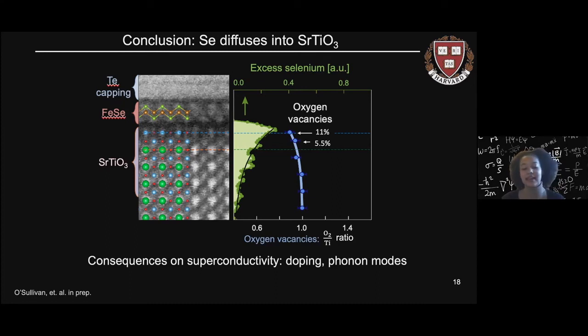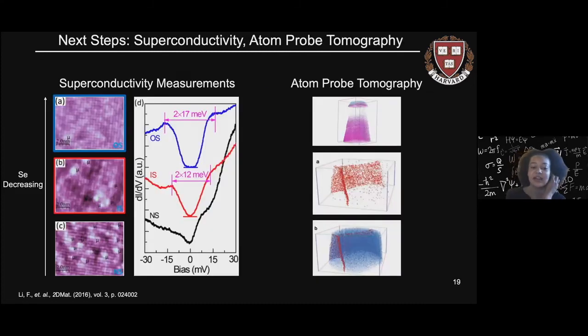But the one study that I present on this next slide here did find that a decreased presence of selenium increased the presence of the superconductivity, which implied that the selenium could be possibly screening the phonon modes. And so decreasing the presence of the selenium would increase the superconductivity as a result. But again, it's a big question to still understand how the selenium presence might impact the superconductivity. So that's what I would say is we don't really know yet, but hopefully we could take next steps to understand that more.